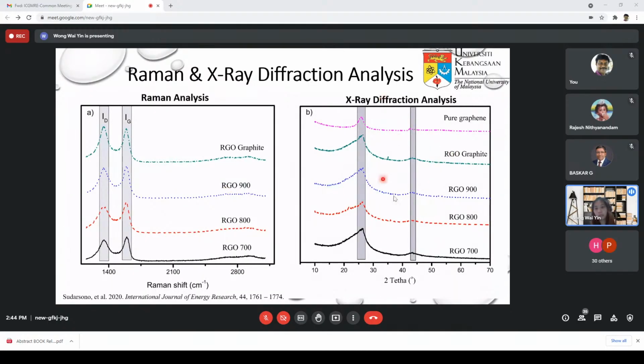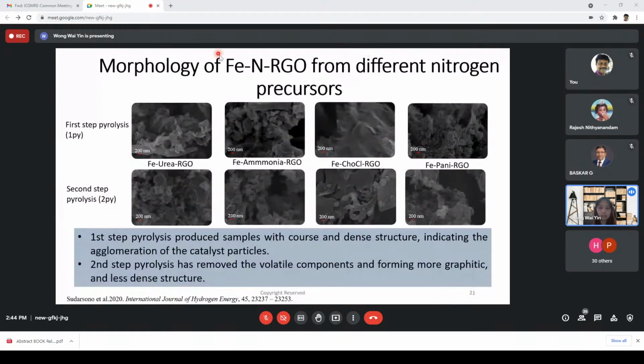Okay, and similarly, we can see that XRD shows very similar patterns compared to the RGO. So this information has verified the formation of the RGO from the biomass itself. Then we select the RGO 900 for further study as the catalyst support itself. So the 4 precursors that we use in these studies consist of urea, ammonia, choline chloride, and polyaniline. Okay, and we added the Fe, iron salt.